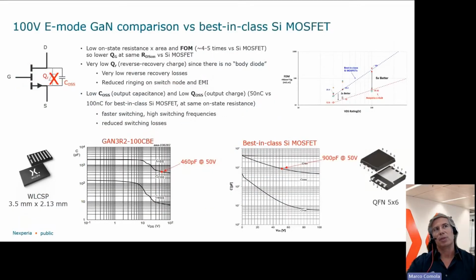And let me go on just to give you some idea, really a quick comparison, of the 100 volt E-Mode GaN versus the best-in-class silicon MOSFET. In that case, you can see on the left side a HEMT, so high electron mobility transistor. And you can see that there is no body diode, so the reverse recovery charge is close to 0. So you have very low reverse recovery losses, and it means you reduce the ringing on the switch node, and this is linked to EMI, so you reduce the EMI, of course.